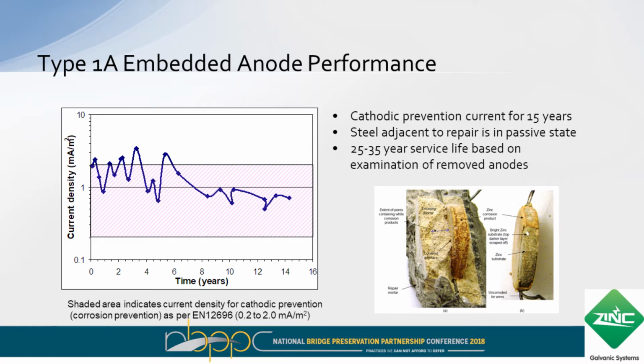15 years of service, some anodes were pulled out of the structure and forensically looked at, and you see the zinc core, which is corroded over time. The zinc corrosion products are moving into the surrounding alkali mortar, and just being able to measure the amount of current over time that's coming off the anodes.